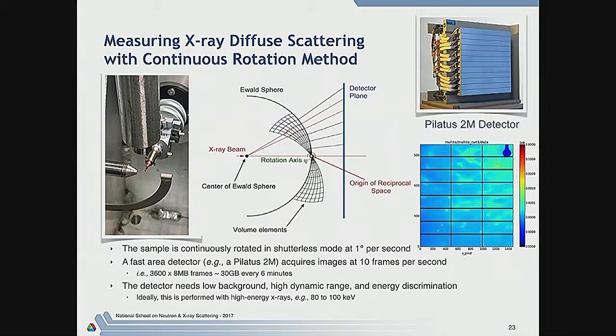Okay, so with X-rays, measuring diffuse scattering is actually now not that difficult. We've just been using a classic technique that protein crystallographers use. You just put the sample in the beam here. This is the beam coming in. This is the beam stop. And we rotate the sample continuously around this phi axis here. Sometimes we have a cryocooler to cool it down. But we have a detector here. In particular, this is a fast area detector, a Pilatus 2M, which is collecting frames while the sample rotates continuously. So we can collect frames at 10 frames a second on this Pilatus 2M. You can go even faster, but we don't. So you can do a full rotation in 0.1 degree steps in about 6 minutes, okay? That's 3,600 frames, each one of them about 8 megabyte TIFF files, 30 gigabytes in 6 minutes.